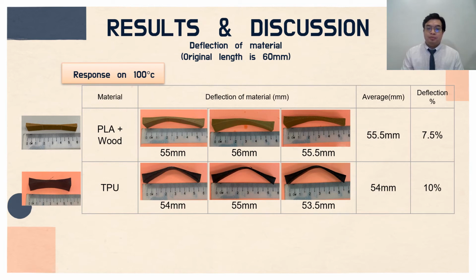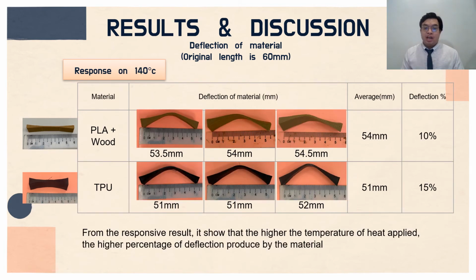And for the third temperature applied on the specimen, which is 140 degrees Celsius, we can see the largest deflection, which is 6 mm for the PLA plus wood and 9 mm change from 60 mm for TPU. And it shows 10% deflection for the PLA plus wood and 15% for the TPU. From the results, it showed that the higher the temperature of heat applied on the specimen, the higher the percentage of deflection produced by the material itself.